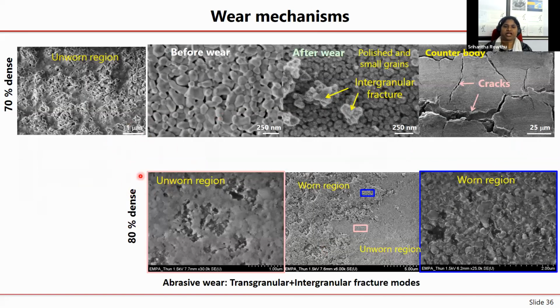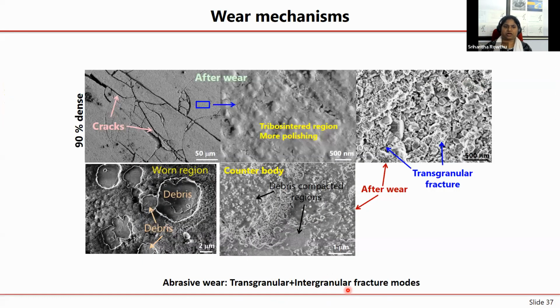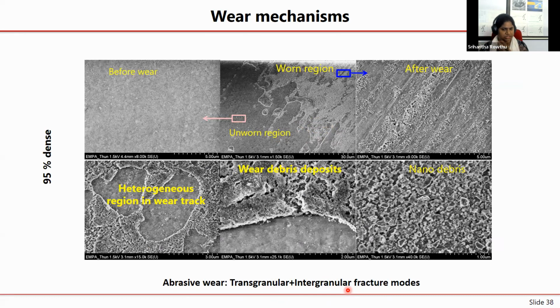Yeah, so then we have looked at the wear mechanisms for all the samples investigated in detail, both the counter bodies as well as the bottom sample, and in fact also the wear debris, and have found out that all the samples are undergoing an abrasive wear mechanism, and the wear is occurring through these 2 modes, which are transgranular plus intergranular fracture modes. However, for the 70, 80 and 90% dense specimens, it is predominantly intergranular fracture, that is the fracture is through the grain boundaries, because these are the weakest points. However, for the 95 and 99.5% dense specimens, these are all the SEM pictures, but I'm just giving you a final conclusion, right?